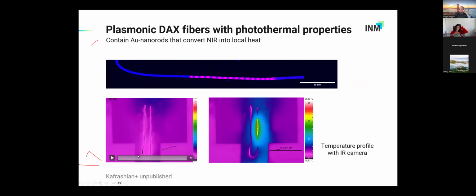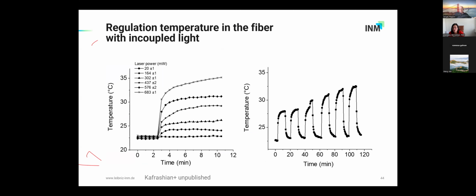If we don't use scattering particles, but we use plasmonic particles, then we can use the same approach to achieve a fiber with photothermal properties. Here you see a fiber which has segments containing plasmonic particles, and they can be heated up with light and also produce localized heating. You can also change the laser power and control how much you heat, and you can do that also in cycles and repeat it. So you can stop heating and activate heating again with light.